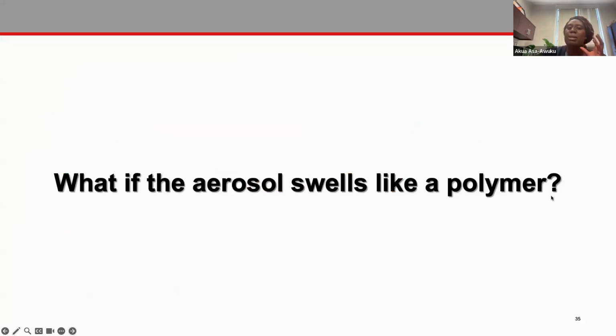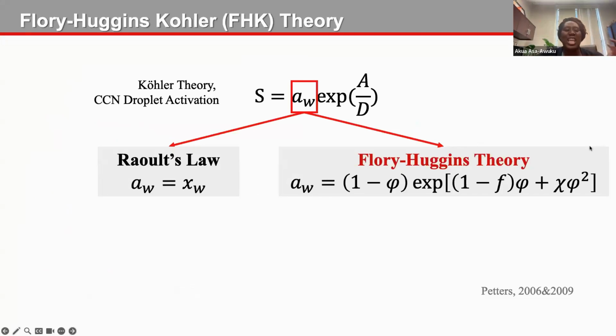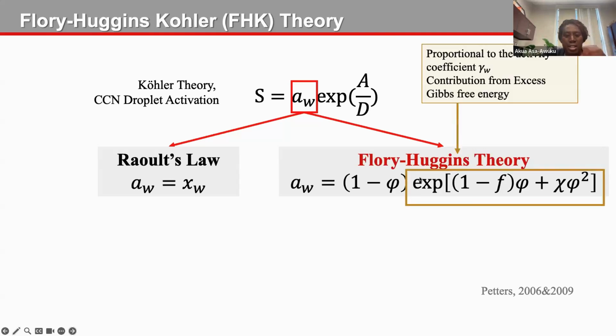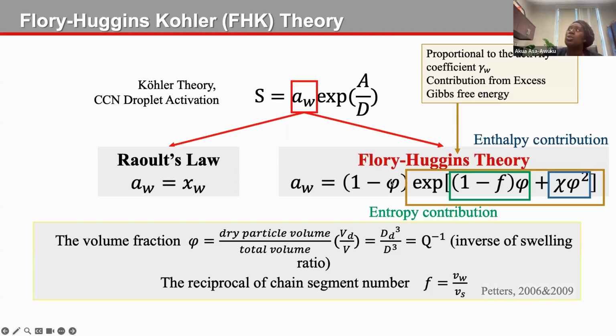Okay, but we believe them to be polymers, right? And what we know about polymers is that polymers can swell in the presence of water. So do we have a model that describes that? And again, we do. It's called FHK, Flory-Huggins Köhler theory. Flory-Huggins Köhler theory was first presented by Petters in 2006 and 2009. What it does in that model is it shows that the water activity can now be described by these polymer interactions, the Flory-Huggins theory, which is where that comes from. And essentially, there are additional parameters that are related to the excess Gibbs energy for dissolution and also to the entropy contribution, which is what you get from the swelling. What's neat about this swelling ratio is that it's a function of the molar volume. If we know the density, it's really a function of the molecular weights. And so one can infer molecular weights with known densities from this polymer theory.